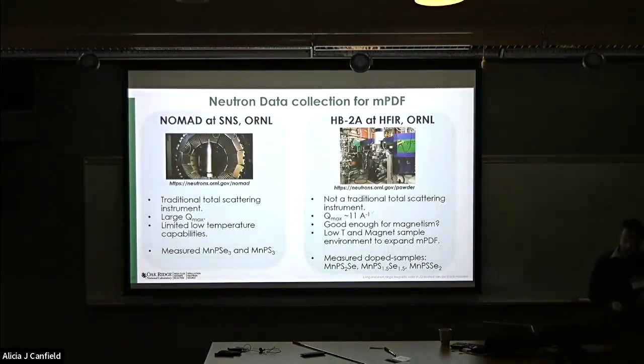So the two neutron instruments that we used, Nomad, this is really the standard, the traditional PDF instrument. You get to very large Qmax. The higher the Qmax you get to, the better the resolution you get in real space. The problem with this instrument is it has limited low temperature capabilities. So if you want to look at quantum materials, if you want to look at transitions below 1 Kelvin, you can't do it. You can't apply pressure, you can't apply field, and so forth.